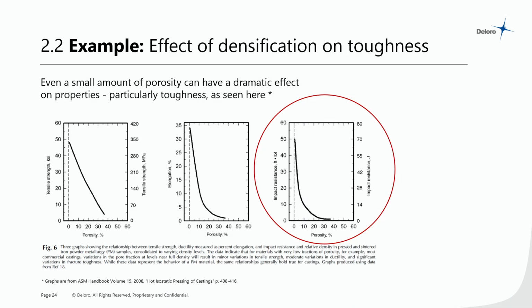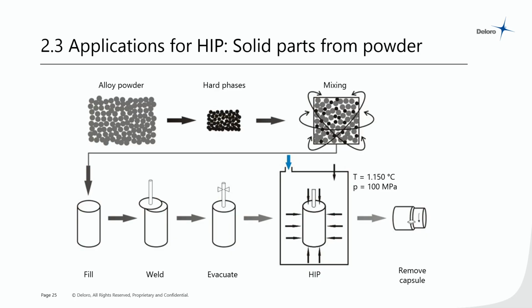Similarly, the graph circled on the right shows you just how exponentially toughness depends on porosity. So you have the percentage porosity on the x-axis, you have the impact resistance on the y-axis, and as the porosity goes up to even just 2 or 3%, you have a massive decrease in the toughness of the component. So that's the densification of cast or PM parts.